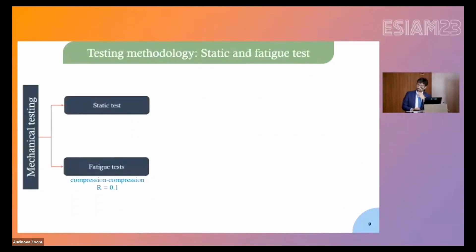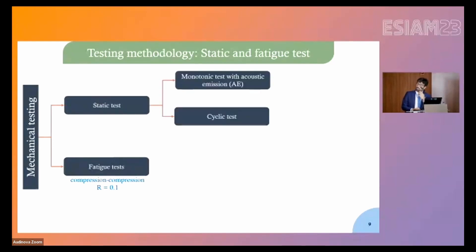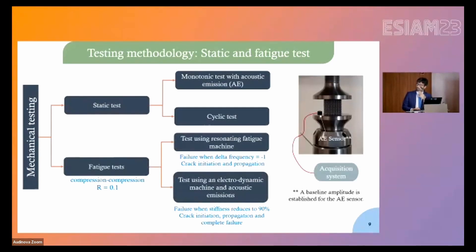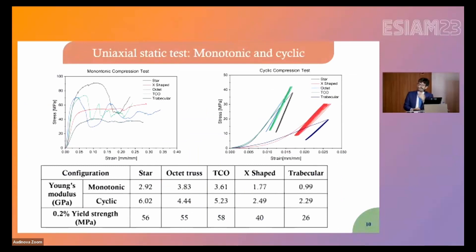We carried out both static and fatigue tests under compression-compression axial loading, including both monotonic and cyclic static tests — the latter to determine the stabilized cyclic Young's modulus. Fatigue tests were carried out using two distinct machines: a resonant testing machine operating at high frequency to collect data in reasonable time including long fatigue lives, and an electrodynamic machine instrumented with acoustic emission sensors positioned on the compression plate close to the coupon.